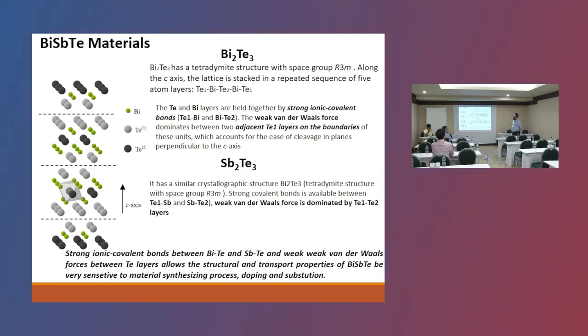Actually, before we did this analysis of the thermoelectric properties, I expected that maybe it would not go into the bismuth, but it could create some nanostructure and decrease the lattice thermal conductivity. That's why we expected the thermal conductivity to be much lower. But as you see here, in all dopants, it acts like electron donation, so it changed the electrical conductivity much more than it decreased the thermal conductivity. That makes me a little confused, because if it does not go into the bismuth site, how did it change the electrical conductivity so much?